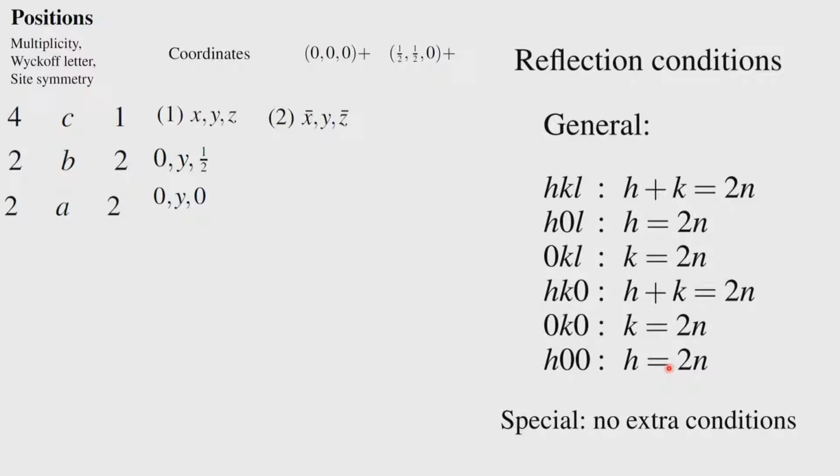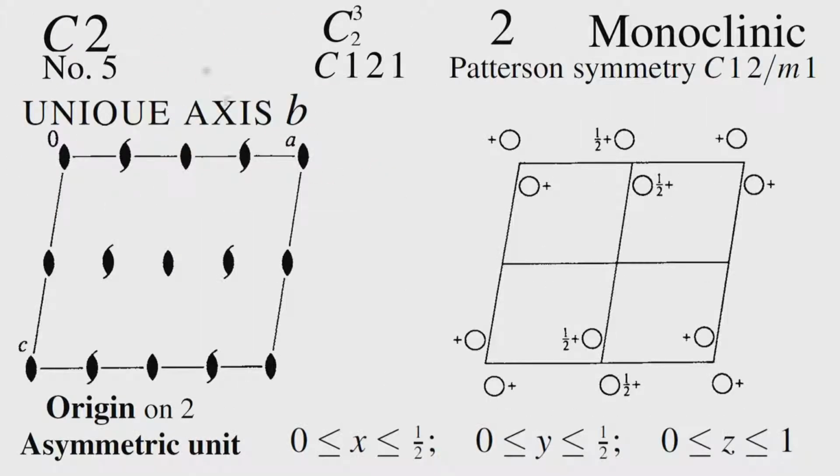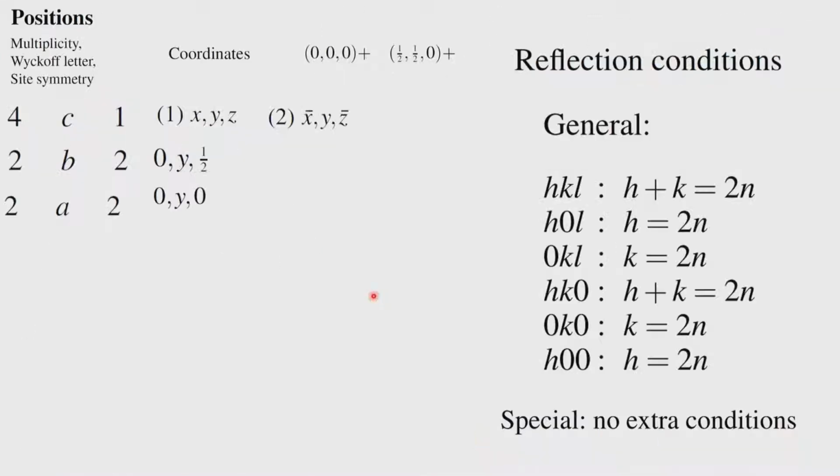What is very important is that if you look at this particular diagram, there are screw axes 1/4 removed from the origin. It is not a consequence of these screw axes, which come as a special case because of the presence of the C centering. So this is the 2 1 screw axis which will develop at 1/4 the distance as a consequence of C centering. This has nothing to do with the systematic absences which you see here.